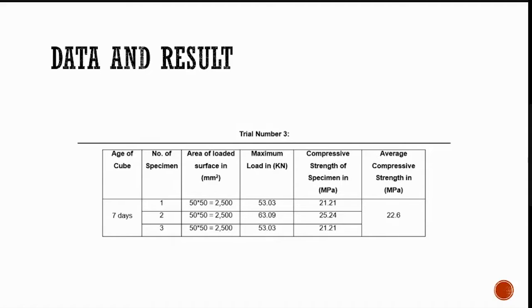In trial number 3, it's also 7 days. Number of specimen is also 3. First specimen, area of loaded surface is 50 by 50 equals 2,500, and maximum load is 53.03. Compressive strength of specimen is 21.21.